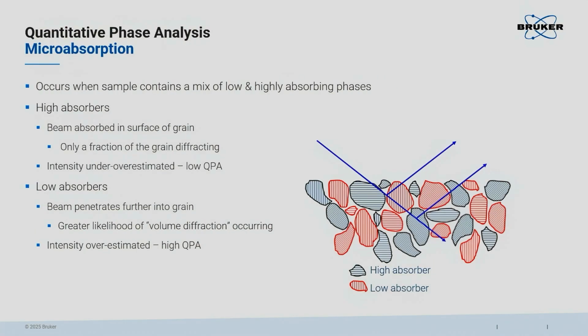So let me talk about the microabsorption effect first. For high absorbing materials, what you will find is that the beam will be absorbed more at the surface of your sample. Only a fraction of the grains will diffract, and the intensity of such phases with high absorption will be underestimated. So in general, the quant results of high absorbing phases will be underestimated, and for low absorbers, it's just the other way around.